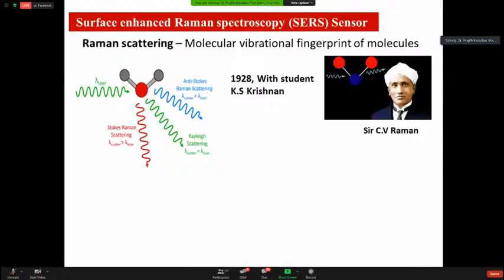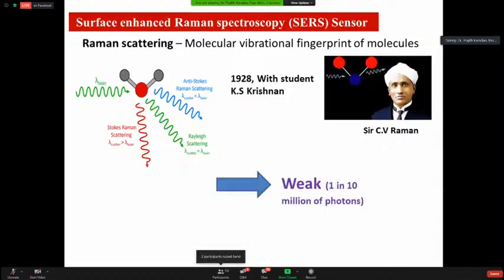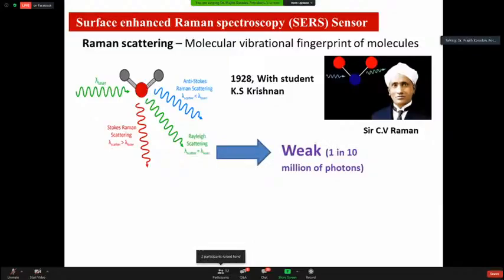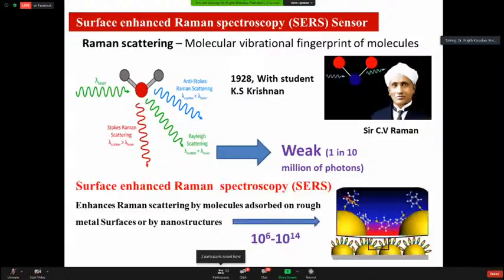This effect was discovered by our own renowned scientist, Sir C.V. Raman, who was awarded the Nobel Prize in 1930 for his discovery with his student K.S. Krishnan in 1928. Typically these Raman signals are very weak. The probability of Raman scattering happening is about 1 in 10 million photons. To overcome this difficulty, people started working on surface enhanced Raman spectroscopy, which enhances the Raman scattering of molecules adsorbed on rough metal surfaces. The enhancement can be from 10 to the power 6 to 10 to the power 14, depending on the nanostructure you are using for making the sensor.